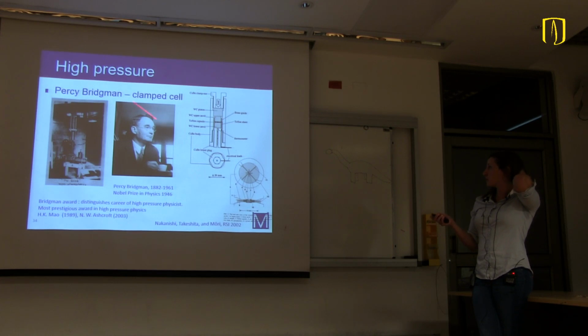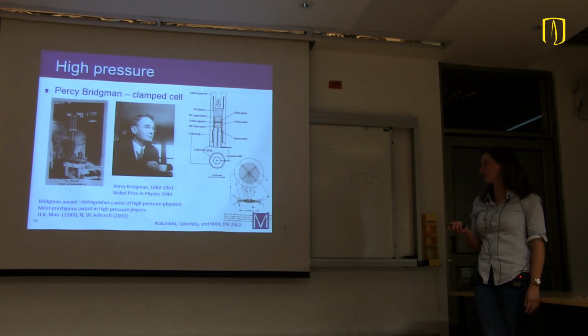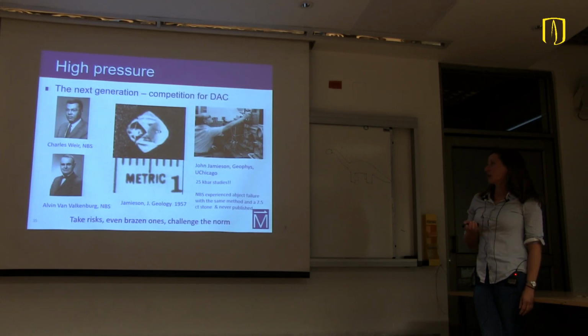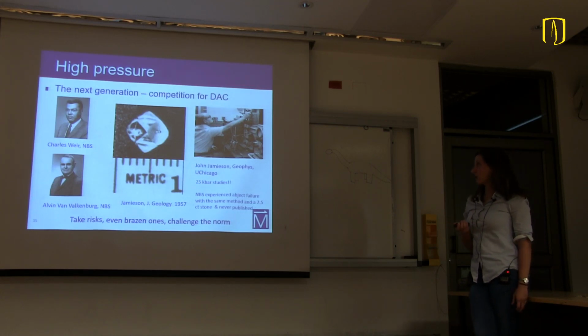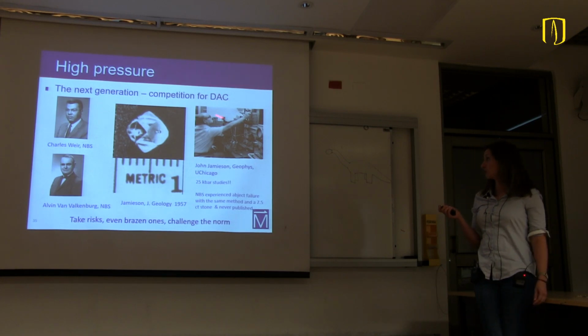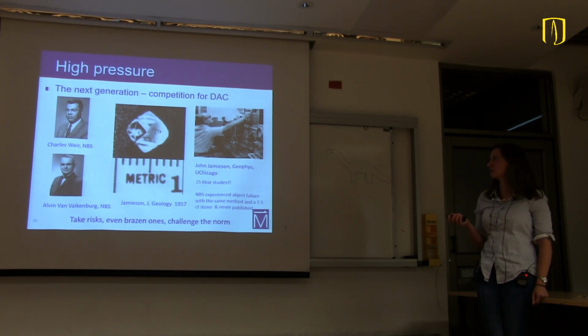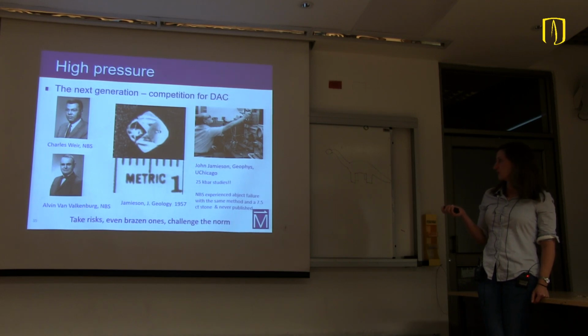So Percy Bridgman did some work in the 1930s, 1940s. And the next generation of high pressure physicists actually developed the DAC, the diamond anvil cells. It was really a race between several groups: the National Bureau of Standards with Van Valkenburg, and the Geophysical Lab in Chicago. This is a picture of one of their first diamond anvils that they used. At the time it was massive, around, I guess, 1 centimeter. And they did manage to create the first diamond anvil cell to get to 25 kilobar.